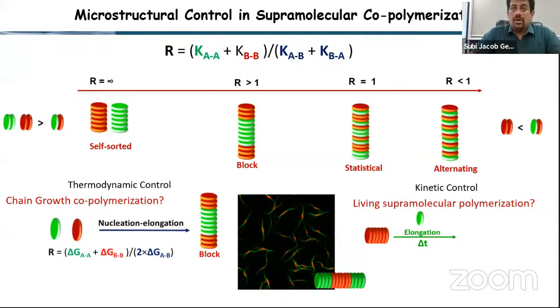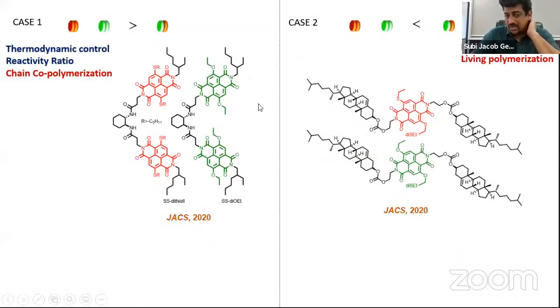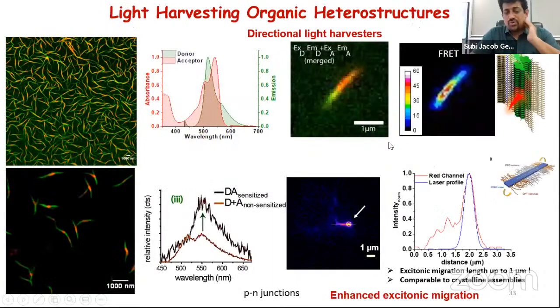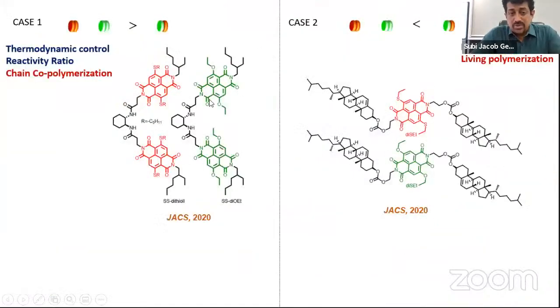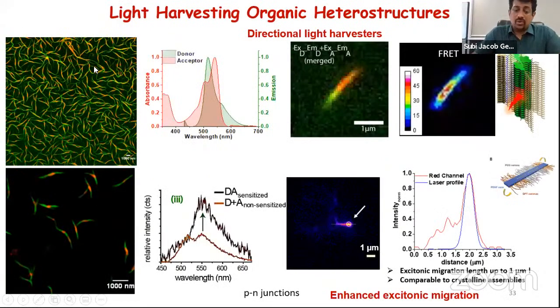But when it comes to chain supramolecular polymerization, it's the free energy of interactions between the monomers. So how to do it? We have also calculated many of the things, and we are working with these kind of molecules. But I just wanted to show one outcome of this. You can see that these are the two supramolecular block copolymers, or axial organic heterostructures, we made with green and red emissive monomers. These are the monomers. You can see that these are well-known n-type semiconductors, naphthalene diimide structures. Just by modifying the core, you can get different spectral properties of these core-substituted naphthalene diimides. So we use them as monomers, and then we can create these kind of axial organic heterostructures.